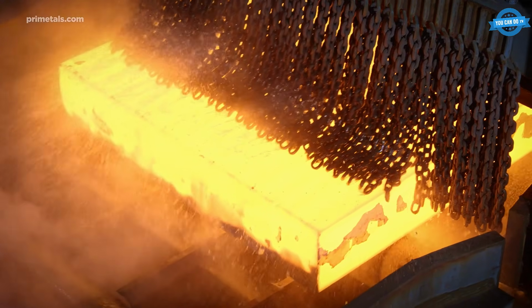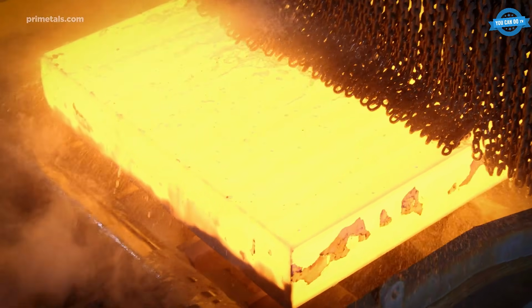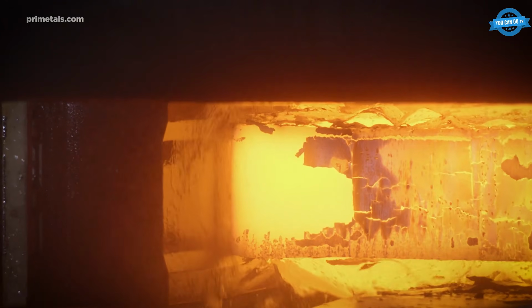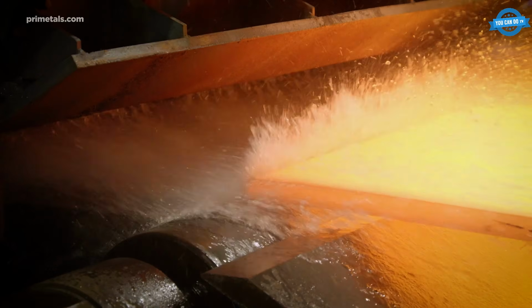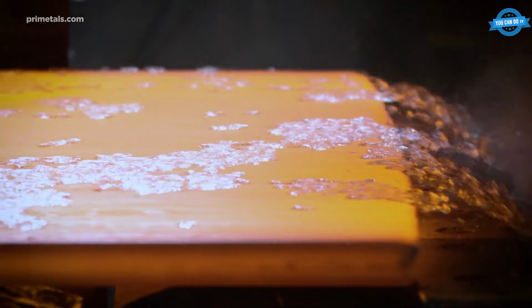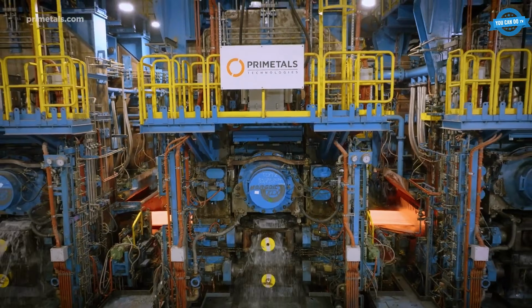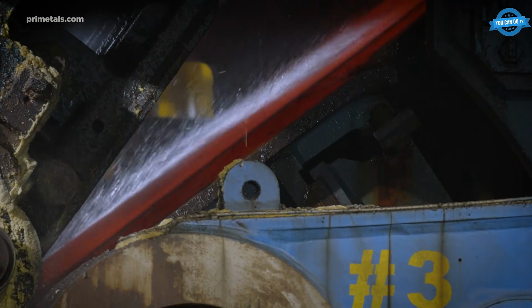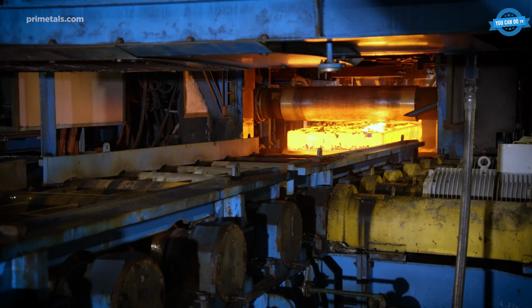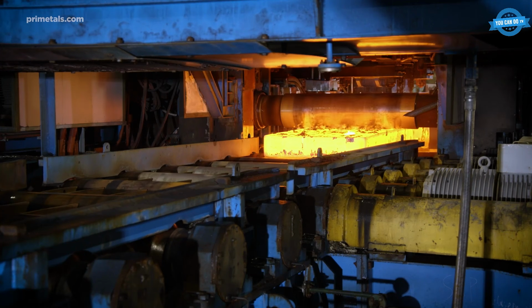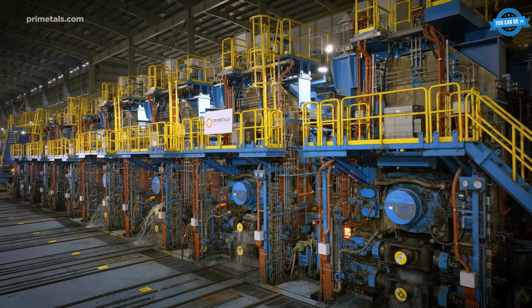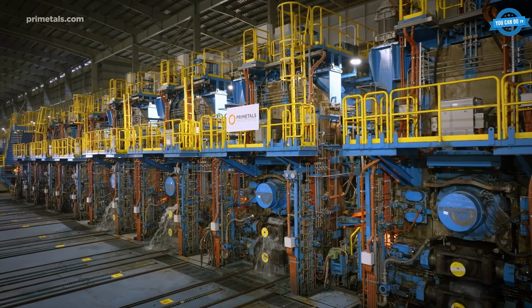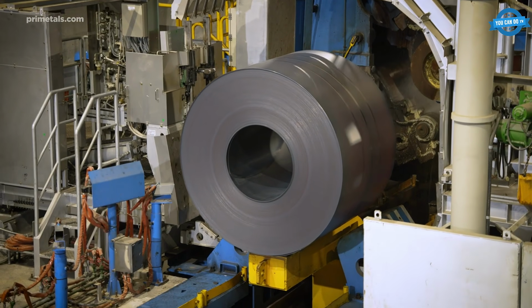From the ladle furnace, the liquid steel heads to continuous casting. Molten metal pours into a water-cooled mold, solidifies into a slab or billet, and slides out the bottom as a continuous ribbon of glowing red steel. A single modern casting line runs almost non-stop for days at a time. The output gets cut to length by an automated shear and stacked, ready for reheating and rolling.